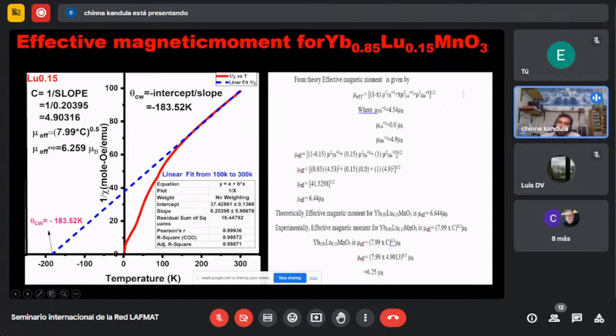I show every calculation here, because lutetium 3+ is diamagnetic, so its net magnetic moment must be 0, and the Yb 3+ oxidation state gives 4.54. Finally, I got an effective magnetic moment of 6.44 μB. That means my theoretical and experimental values are almost close. Sometimes the experimental value is lower than the theoretical value, and that trend is observed in many papers. So I'm good: my sample synthesis went well, and the theoretical and experimental effective magnetic moments are in good agreement.